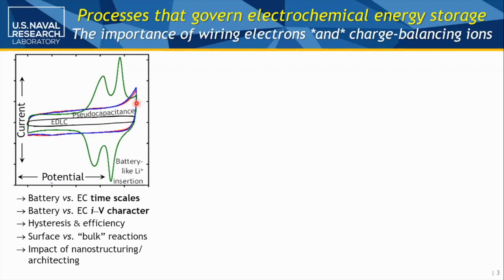And you get a hint that, yeah, there might be something Faradaic going on at the ends and occasionally in the middle. And a true battery gives us thermodynamic peaks that relate to where is the change in the redox center in the active material. So timescales matter. There's that pattern recognition event of what the current voltage curve looks like. Supercapacitors can give you hundreds of thousands of cycles because you're not changing much physically. It's just going to the surface. The Faradaic reactions are involved, and you have to worry about the efficiency, the coulombic recovery, charge discharge.